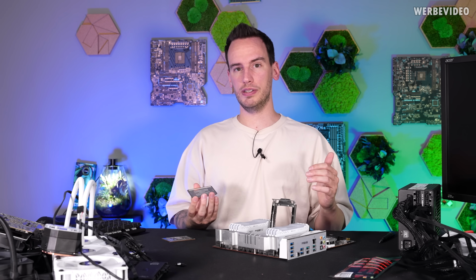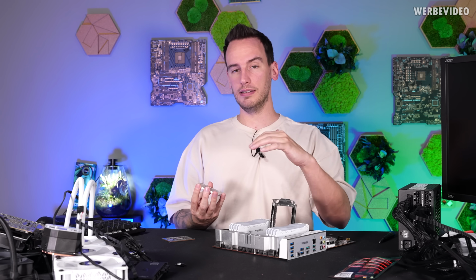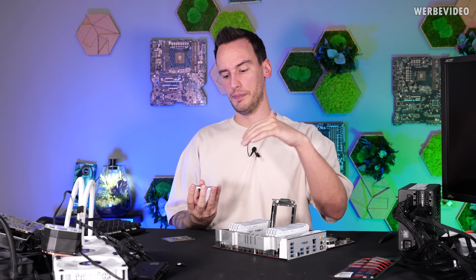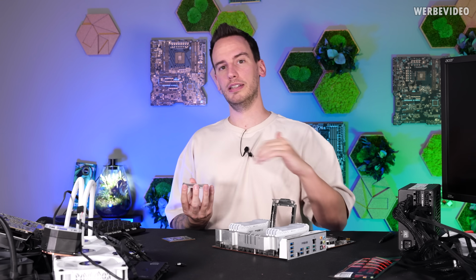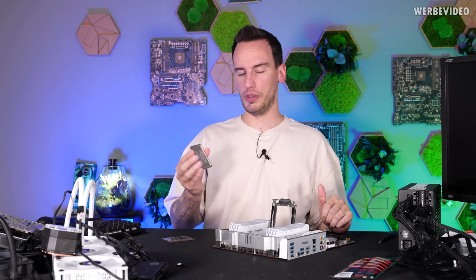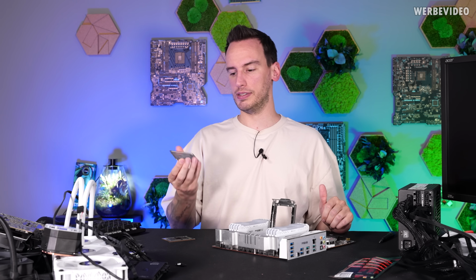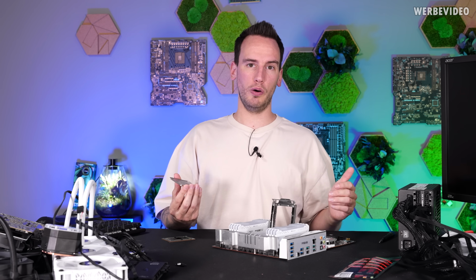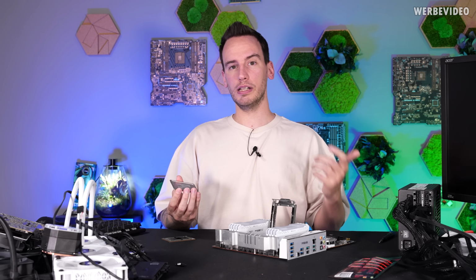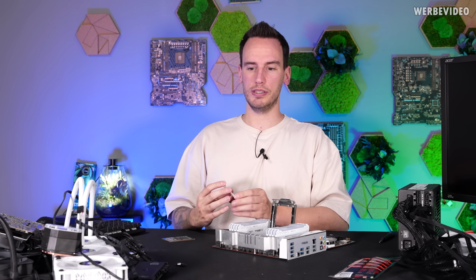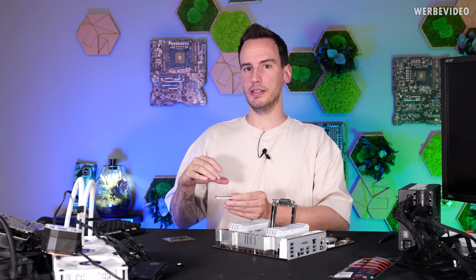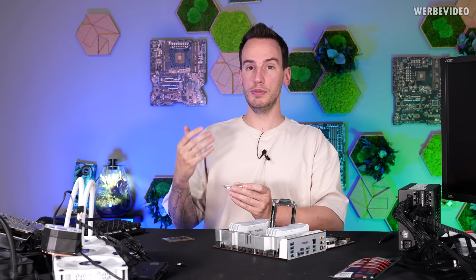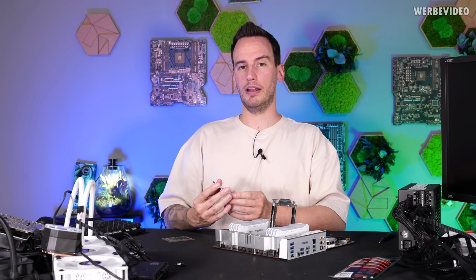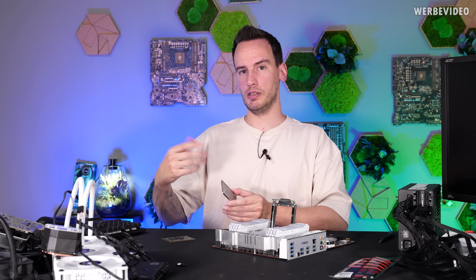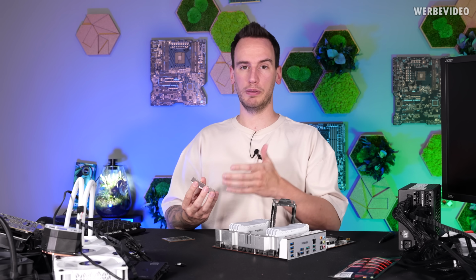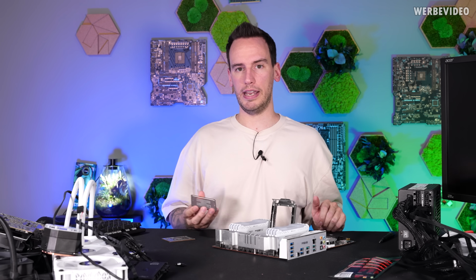We see the surface embrittlement, that is basically the gallium eating into the gold layer first and then into the copper. And without the proper preparation of the surface, that is just what happens. Now we know, years later, that even the nickel plating that's currently used on a lot of coolers is still much better than this, but it's not sufficient. It's not immune against liquid metal alloys, but it's significantly slowing down this kind of embrittlement process that we're seeing on this IHS, for example.